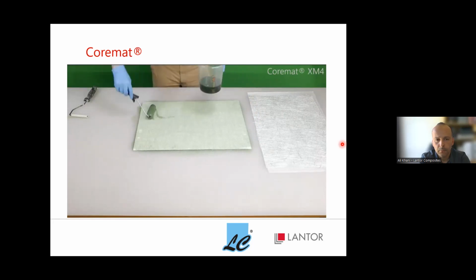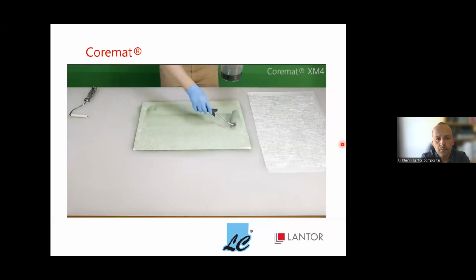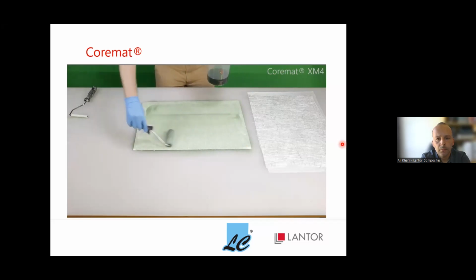We do not have to measure the amount of resin we use because it's not possible to overfill the core mat. The structure of the fibers and microspheres are chemically bonded to each other, so it will not expand when resin is added.